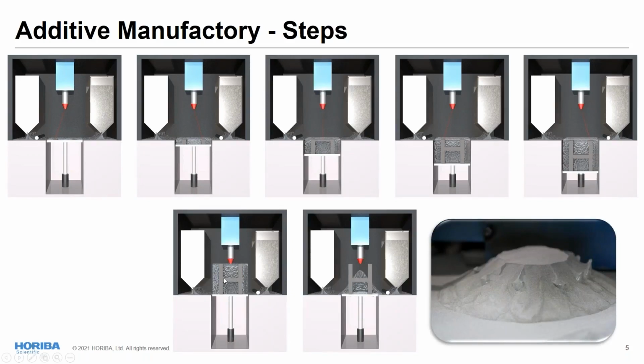So at the end of the process, you have your object printed here in the bottle, which is brought up, and you see you have a lot of metal powder here that was not used in the printing. Some of it will remain free flowing from the object, and this is how an object looks just after it's printed. You transfer that to another chamber that is controlled, so that you don't have direct contact with the particles because they're too thin, and you vacuum out the residue. But usually with both systems, regardless of whether you use laser or electron beam, you're going to need some sort of treatment. It can be mechanical, thermal or chemical treatment, or sometimes a combination of all of them, to have your object as it was supposed to be used.